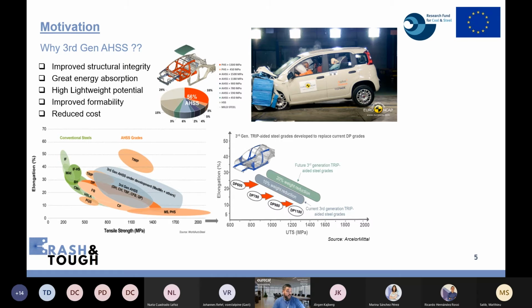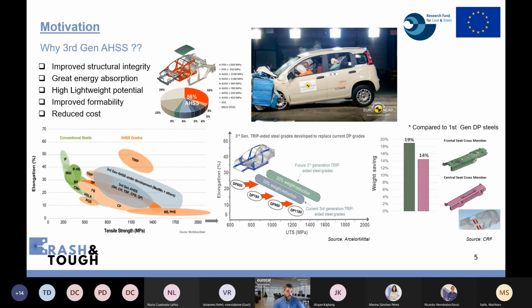Here is some data provided by ArcelorMittal, where they claim that replacing first generation dual phase steels with the current generation of third generation TRIP-assisted steel grades can bring a weight reduction of up to 10%. Then, if we look into the future third generation TRIP-assisted steels, these weight savings can go up to 20%. So we see that there are important weight savings.